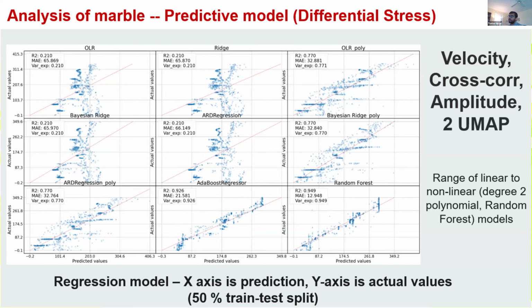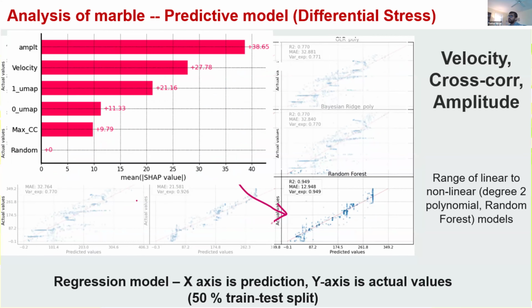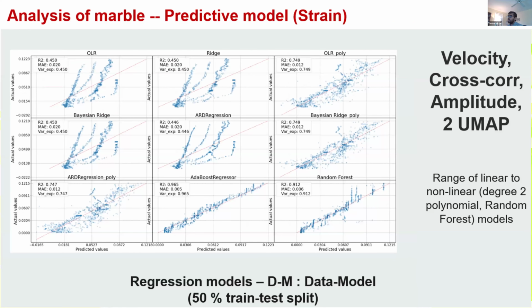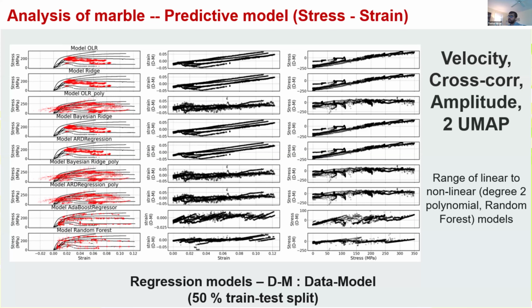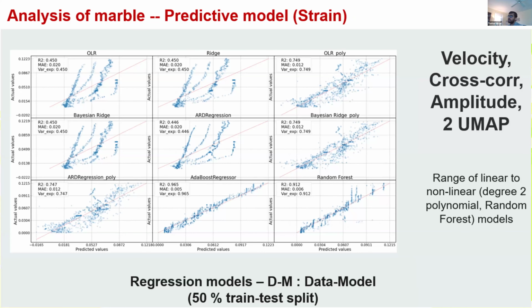We can do the same thing for differential stress. Adding UMAP improves the prediction for the differential stress significantly compared to what we had before. And again, when we look at the feature importance, amplitude, velocity, and the UMAP features are really important in being able to predict the differential stress from just looking at the velocity, cross-correlation, amplitude, and the UMAP. Then we do the same thing for strain. Again, you can do a pretty decent prediction.